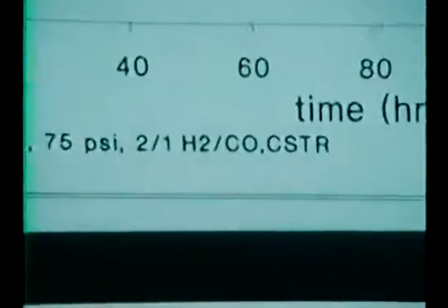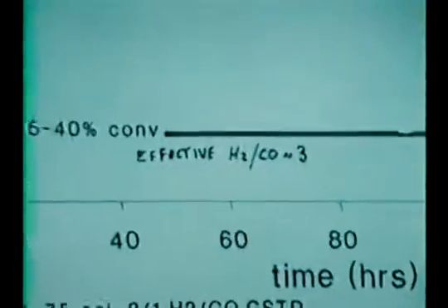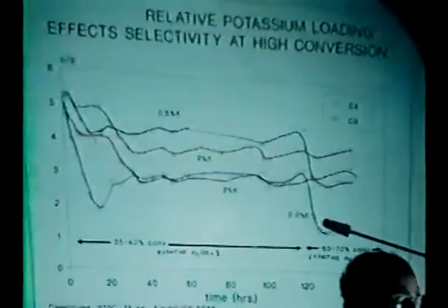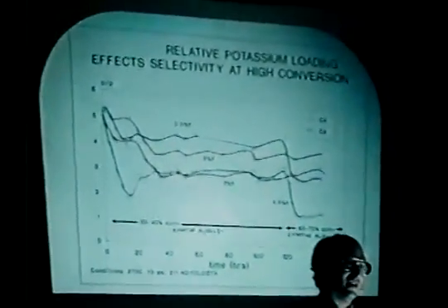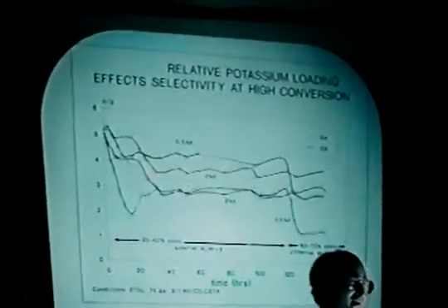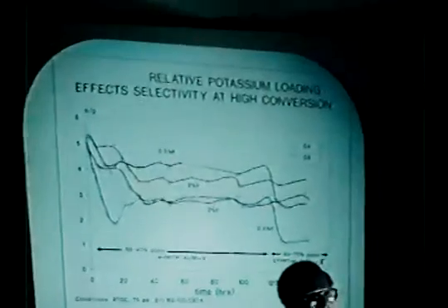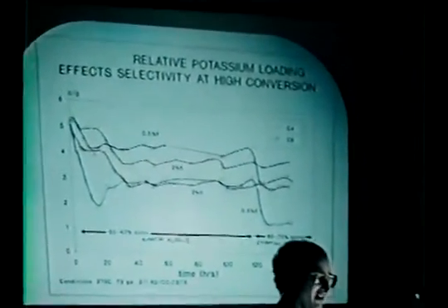And we see that whereas the catalysts behave fairly similarly at low conversions, when we shift to the high conversion conditions, the lower loaded potassium one, the C4, starts to show a lower olefin selectivity. And this at C9 starts to show up even more significantly. Here the purple curve shows the 0.5% loaded potassium for the C9. You can see as soon as we go up to the high conditions, the olefin paraffin ratio decreases dramatically. So this is a very effective test and another way in which the reaction environment interplays with the catalyst bases that are present and affects our selectivity.